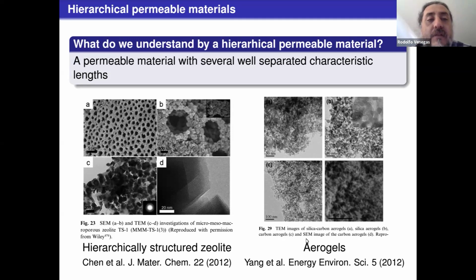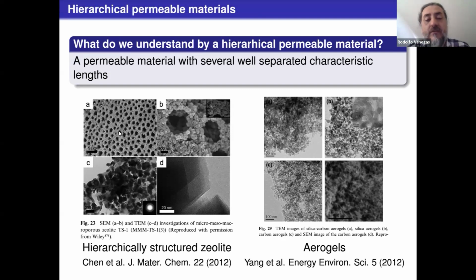So with that, we will start talking about hierarchical permeable materials. By that we understand a permeable material with several well-separated characteristic lengths, like for example this structured zeolite, where we have heterogeneities at the very nanoscale, this 20 nanometer scale, and here we have a 1 micrometer pore. These materials may come in granular form, so we have the size of the grains, and that's another characteristic length. So we have at least 3 scales of porosity here: nanoscale, microscale, and then mesoscale around these grains.